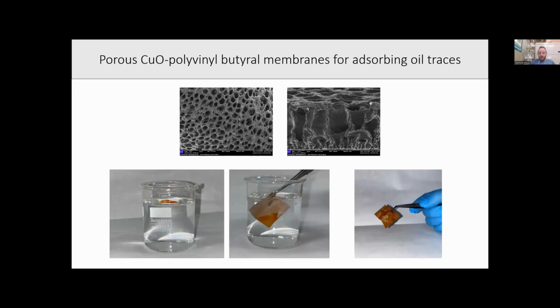Here you can observe the top surface and the cross-section image of the polyvinyl butyral doped with copper oxide nanoparticles. You can observe the porous structure, which can be induced by the NIPS process, which is mainly related to the use of a solvent and non-solvent process, and the formation of a finger-like structure in the cross section, which can be used as channels for the removal of different kinds of contaminants.